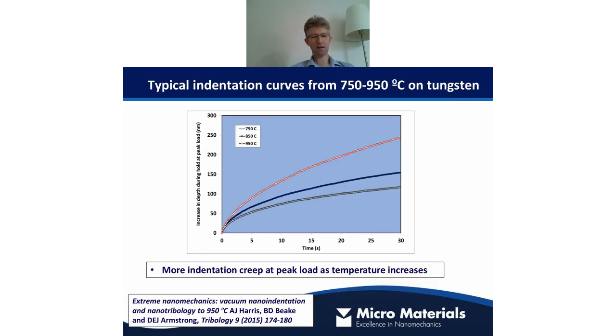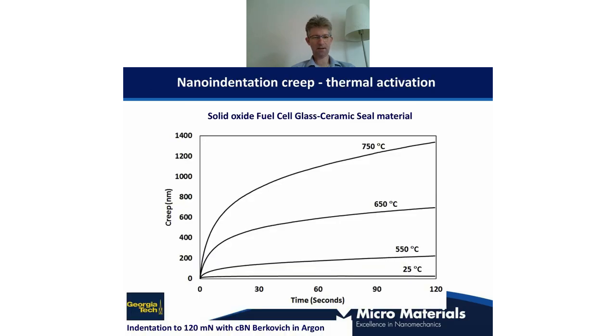As you go to higher temperature on these systems, you get a more increasing time-dependent deformation. So this just shows what happens during a 30-second hold at these different temperatures from 750 to 950. And we can see there's progressively more creep at a higher temperature. We've also seen this in our standard Vantage systems.